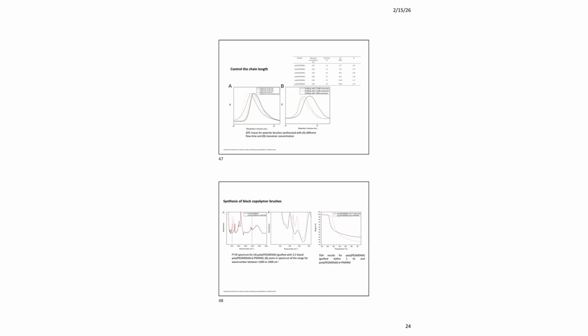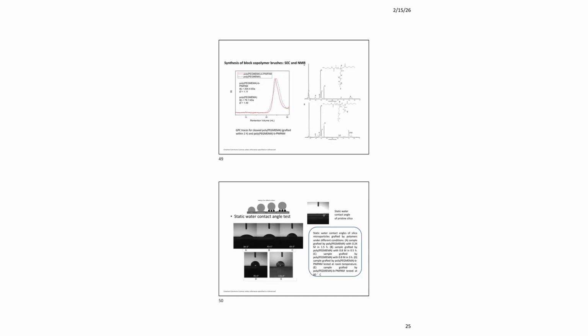For the block copolymer synthesis, FTIR confirms the presence of the second block, PNIPAM, by the appearance of its characteristic amide peaks. TGA also confirms the successful block copolymerization, showing a greater total weight loss compared to the initial homopolymer brush. The most direct evidence comes from GPC, which shows a clear shift to a higher molecular weight after the second block is added. NMR spectra of the cleaved block copolymers further confirm their chemical structure.